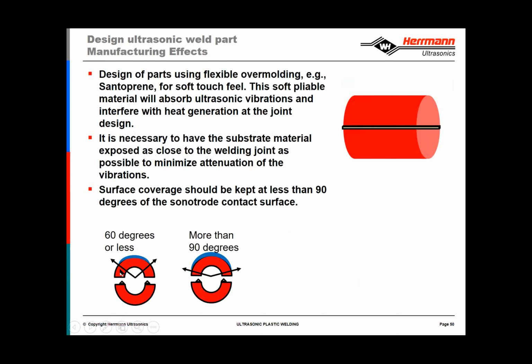And I've got the mouse here up on the part, and as you can see, keeping the overmolding to a minimum, and especially not in the area directly above the welding joint. In the other case where the overmolding wraps around a larger area, we would have to make contact with the overmolded or soft material, which would typically dampen the vibrations and therefore inhibit the transmission of those vibrations to the energy director. So something to keep in mind, that if you have multi-component parts or parts that do have an overmold on them, that access to the welding area should not be inhibited.